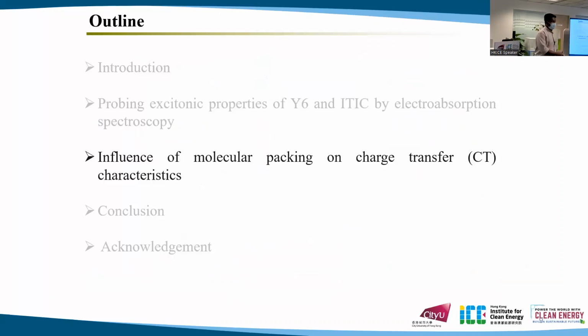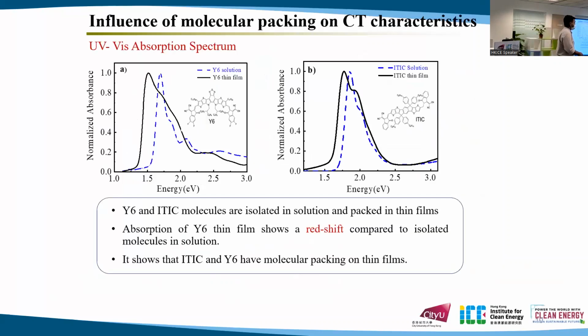Then we are going to see how we can control the molecular packing and understand more about the intermolecular charge transfer characteristics. For that, we did UV visible absorption of Y6 and ITIC non-fullerene acceptors in thin film and solution. And you can see there's a redshift for Y6 and also ITIC, which gives us the primary evidence that Y6 and ITIC show molecular packing in thin films. That means in solution, they will be more dispersed, right?